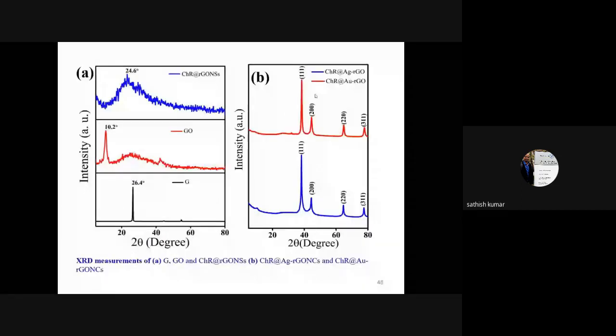Here also, XRD analysis gives some information about the conversion of pristine graphite into monolayer reduced graphene oxide. And also in composite preparation, based on the diffraction planes, here we cannot see any diffraction planes because the graphite is not a crystalline material. But after the hybridization of crystalline material like silver and gold, we can see the diffraction planes corresponding to the face-centered cubic silver and face-centered cubic gold nanoparticles. These diffraction planes were compared with the corresponding JCPDS.